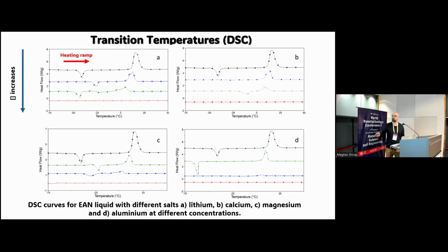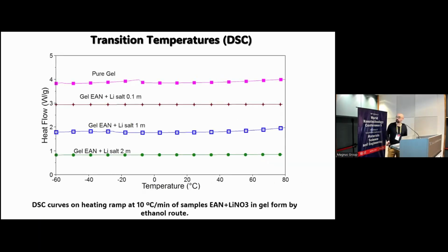You can see how when the concentration of the salt increases, the crystallinity disappears, and there is a kind of amorphous phase in our compound. Even in some cases, we can see the glass transition. The same occurs with the gel. You can see here the pure gel, we have a small peak of melting, but when we add the different concentrations of the lithium salt, this crystallinity disappears, getting our amorphous phase-like compound.